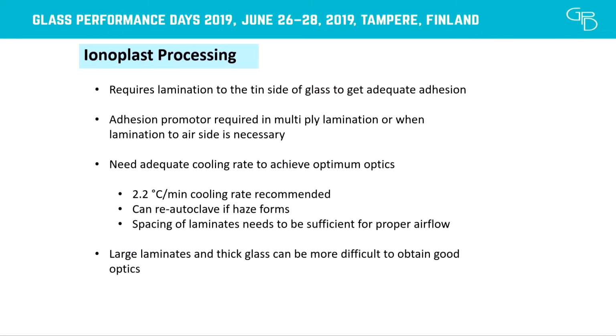So I mentioned that Ionoplast requires some special processing. One of the things is that it requires you to laminate the glass to the tin side to get adequate adhesion. If that is not possible, such as in multi-ply layers or in laminating to frits, you must use an adhesion promoter in order to get adequate glass adhesion.